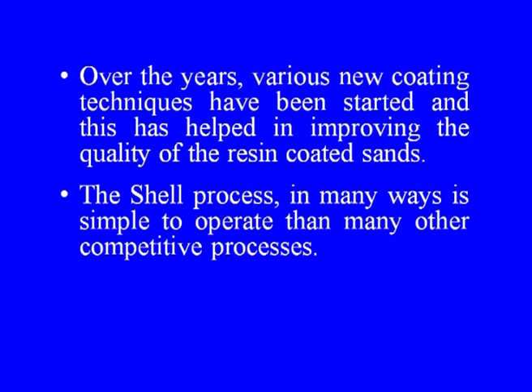In order to overcome these issues, novolac phenolic resin dissolved in alcohol is used and the sand is warm-coated with it. Using this technique, better strengths were achieved with lower resin addition, along with excellent curing characteristics and lesser dust problems. Over the years, various new coating techniques have been introduced, improving the quality of resin-coated sands. The shell process is in many ways simpler to operate than many other competitive processes.